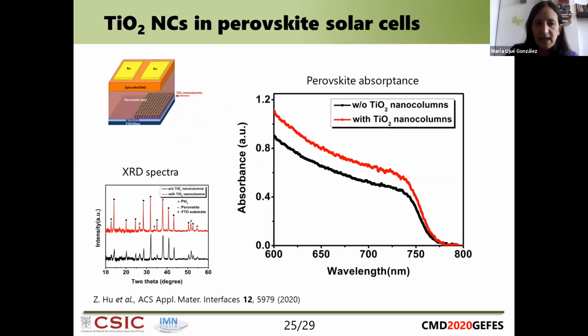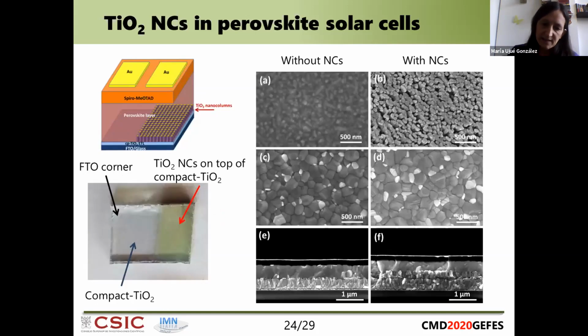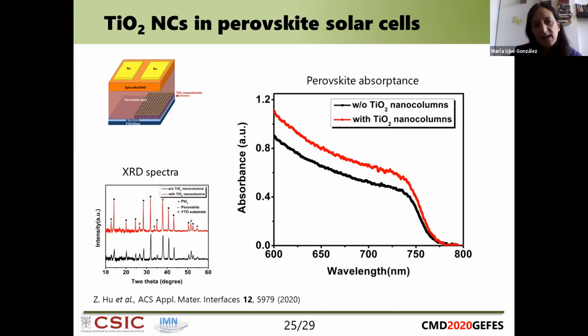The quality was good. And indeed, in the red graph, with the nanocolumns, you see even more peaks in the X-ray diffraction spectra, which means that the crystalline quality was even better, which we think could be because the perovskite was infiltrating within the nanocolumns, generating crystallization points and helping to get an even better structure for the perovskite. So that was helpful. The other important property we found is that when we measure the absorbance of the perovskite, it was also bigger with the presence of the nanocolumns.